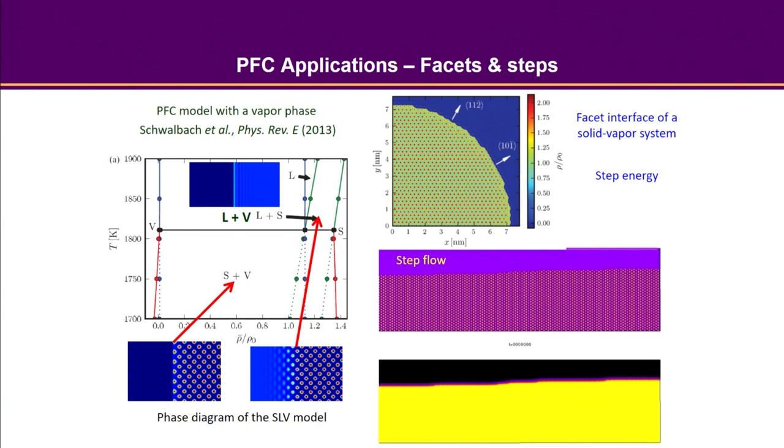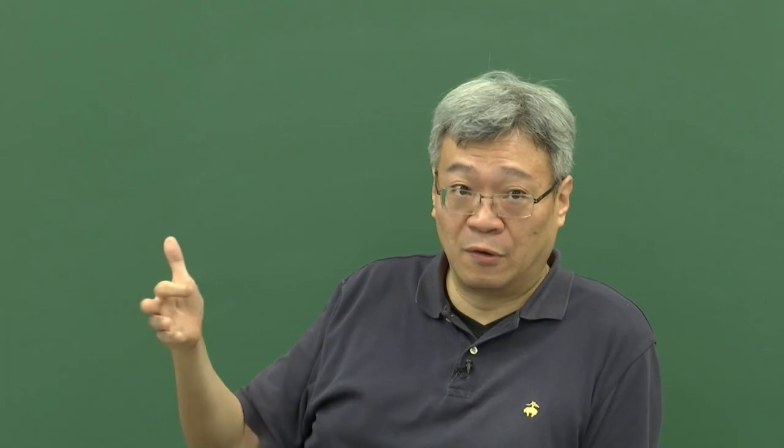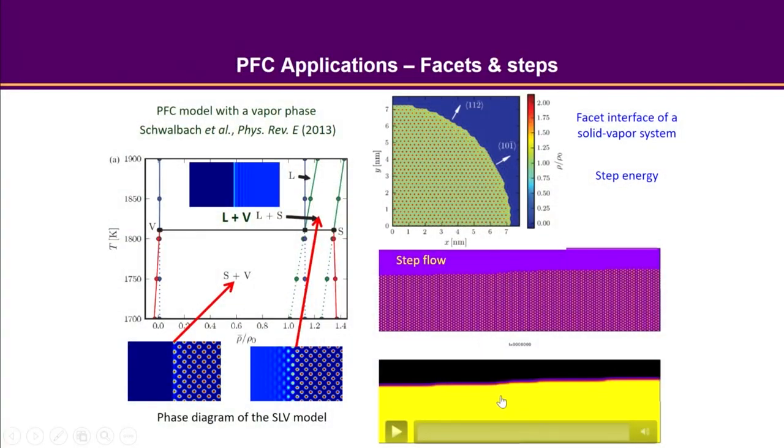I hope you can see clearly that in the very beginning, I intentionally set the size of the step to be different. So you can see there will be a shorter terrace and a longer terrace, right? Those are the shorter ones and these are the longer ones. There's no strain to the solid. So what we are expecting is that there are add-atoms coming on the top. When add-atoms come on the top, the larger terrace has the opportunity to absorb more add-atoms, so you are expecting the step to move faster. On the contrary, you are expecting a rather slower growth for the shorter step. So you can see here, initially we have this uneven terrace size, but later on, when the add-atoms come in, you start to see the size become more and more even.